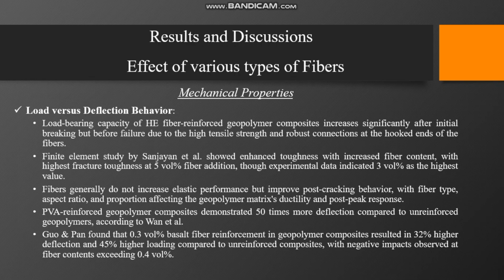The load bearing capacity of the fiber reinforced geopolymer composites increases significantly after initial breaking but before failure due to the high tensile strength and robust connections at the hooked ends of the fibers. Finite element study by Sanjayan et al. showed enhanced toughness with increased fiber content, with highest fracture toughness at 5 volume percentage fiber addition, though experimental data indicated 3 volume percentage as the highest value.